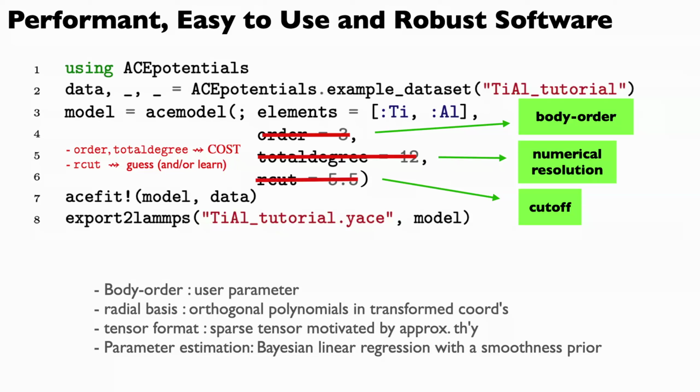It's one of those radii, atomic radii, and then times some factor that empirically over the past 10 years turned out to be a good factor. Okay. And we make it a bit conservative, so we make the cutoff a little bit larger than it needs to be. So that means you increase the cost a bit. And so if you want to really optimize and get better performance out, then you try and squish the cutoff back down a bit.